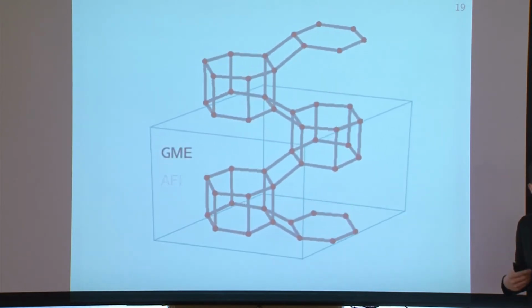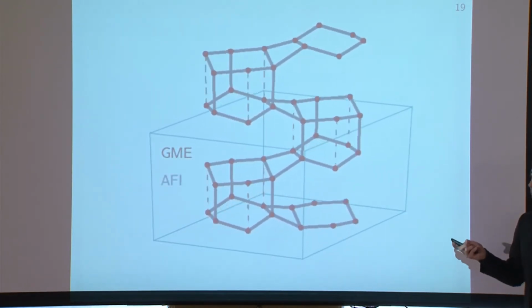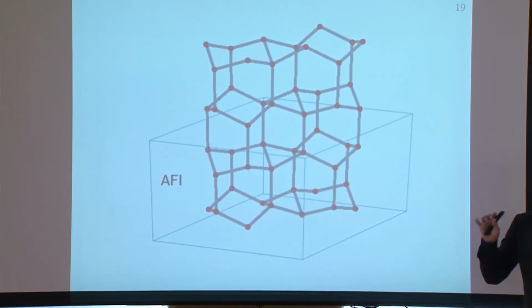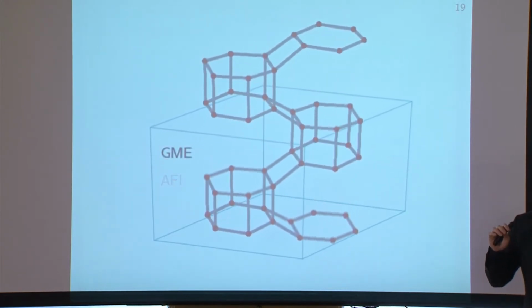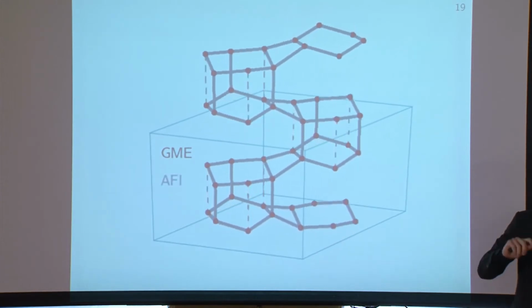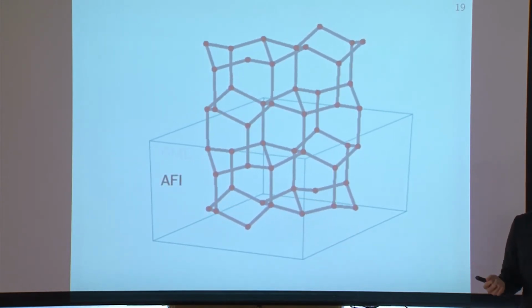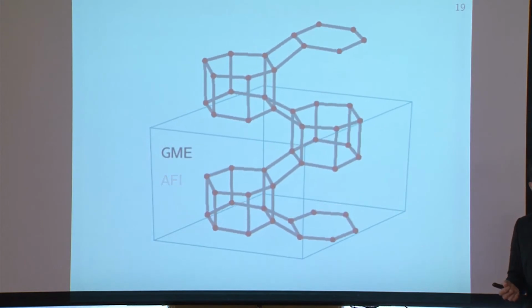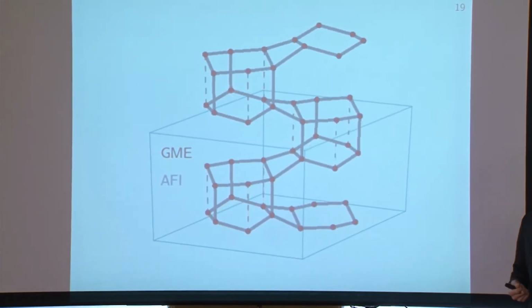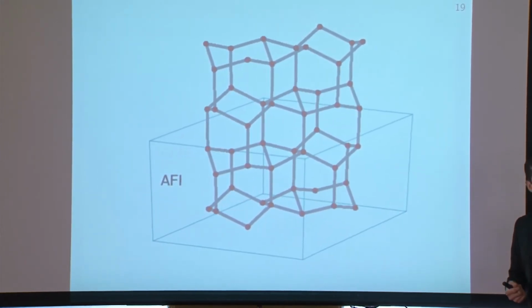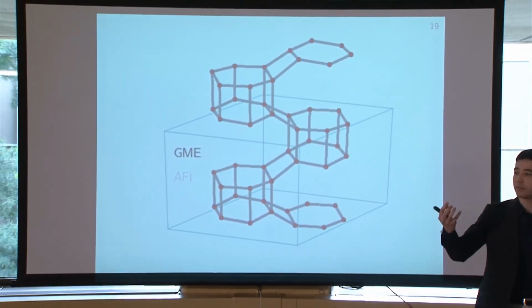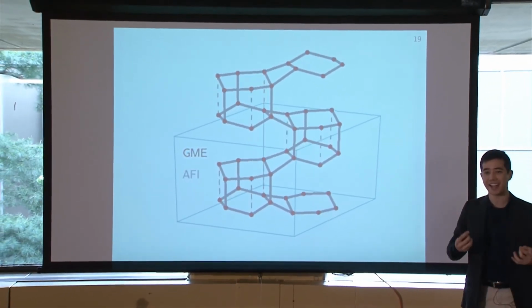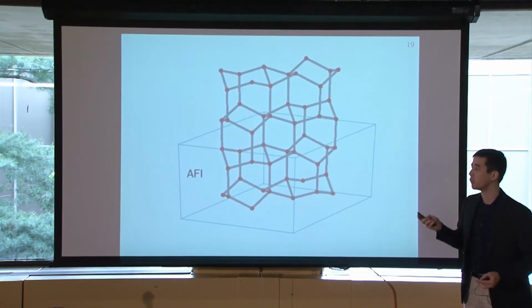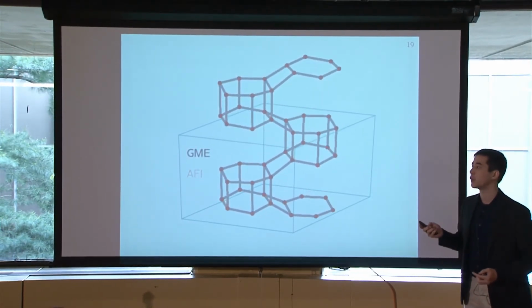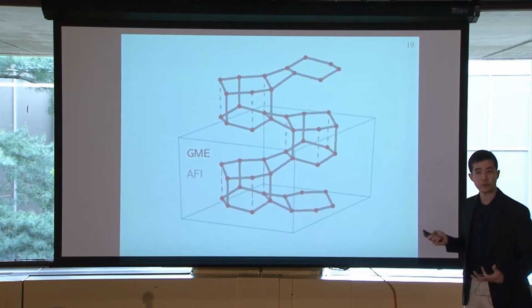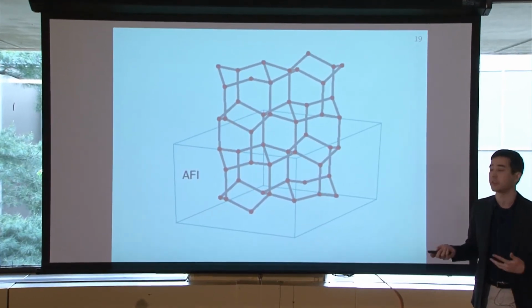And why is this meaningful to us? Well, if two crystals share the same graph representation, it would imply that there is a lower barrier to interconvert such crystals, because not only do they have the same number of nodes inside their unit cells, not only do they have the same number of bonds inside their unit cells, but for each atom in one crystal, there is one equivalent atom in the second crystal with the exact same neighborhood. So it means we could analyze and we could induce such diffusionless transformations within these materials just by looking at